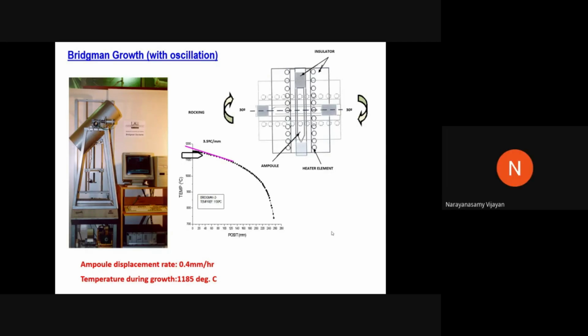Now, another material we have taken, that is cadmium zinc telluride. Cadmium telluride is one of the best materials for detector applications. What we have done is grow the single crystal in laboratory conditions. What are the laboratory conditions? You have a temperature profile, that is common, but you also have gravitational force. Gravitational force, indirectly, sometimes may influence the formation of defects.